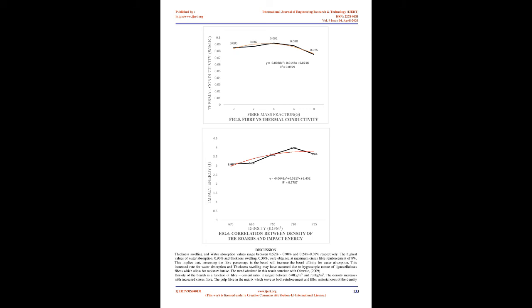Density of the boards is a function of fiber-cement ratio. It ranged between 670 kg/m3 and 735 kg/m3. The density increases with increased Cissus fiber. The pulp fiber in the matrix, which serves as both reinforcement and filler material, controls the density of the boards within the acceptable range of 500 kg/m3 to 800 kg/m3 for medium density fiber board. The polynomial rank correlation, R2 equals 0.78, between density and impact energy of the boards as depicted in Fig 6 indicates that the impact energy of the board is also a function of density of the boards.